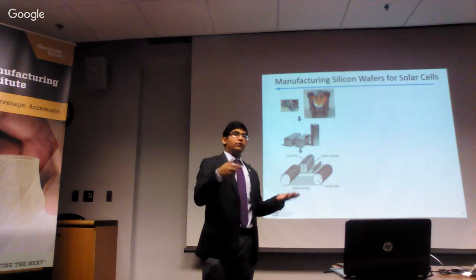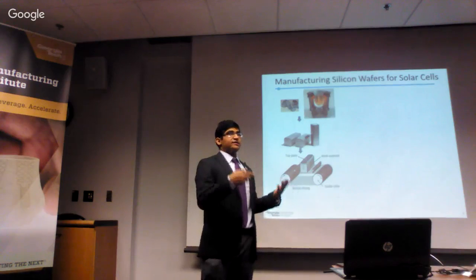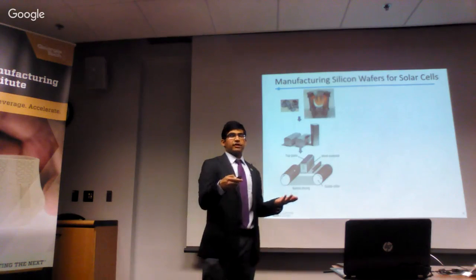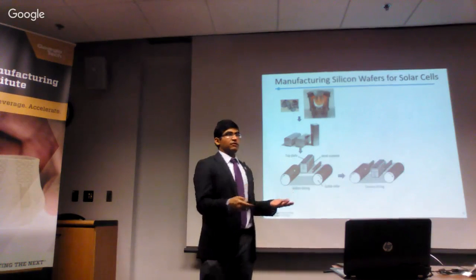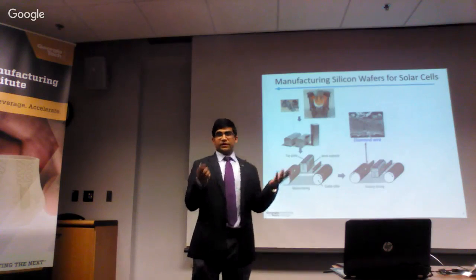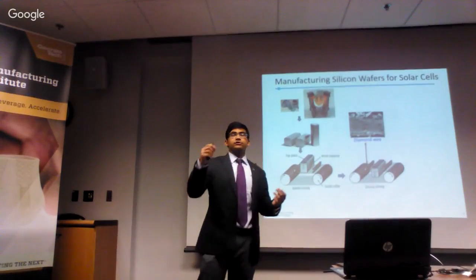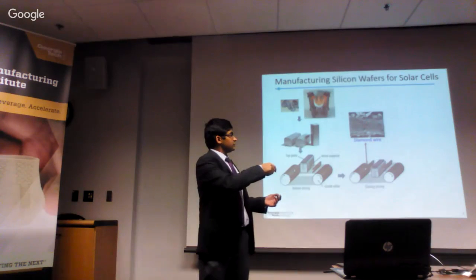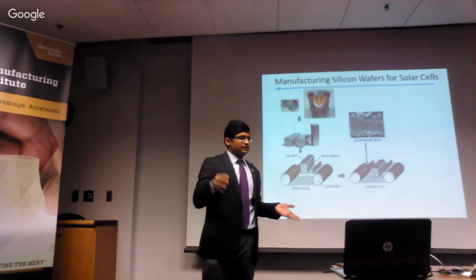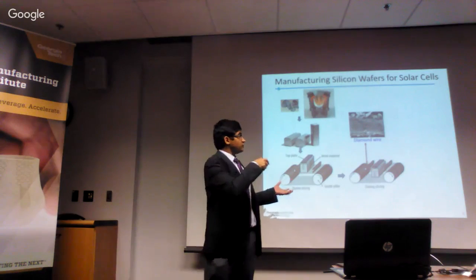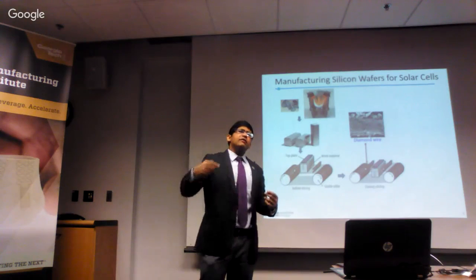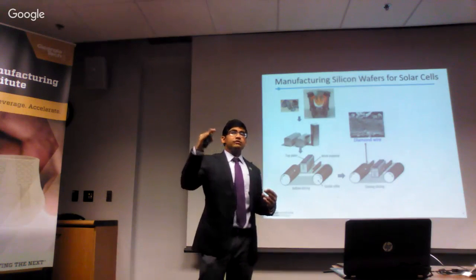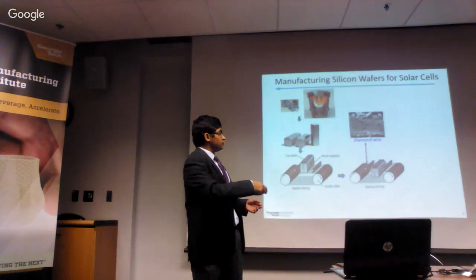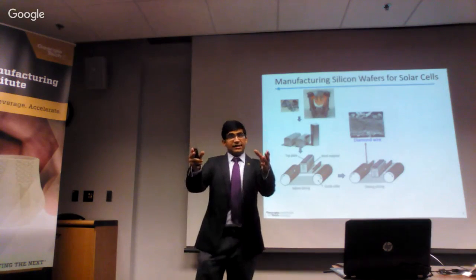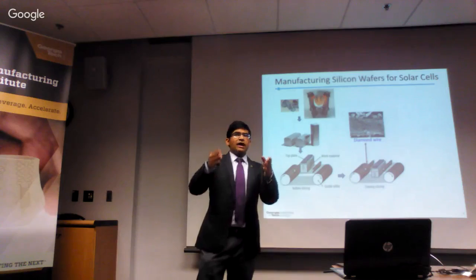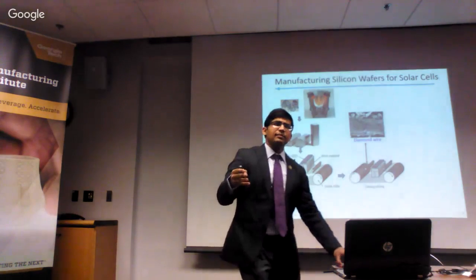Now, both this mono and multicrystalline silicon are then sliced by an abrasive wire sawing process, which consists of tiny diamond abrasives attached to the steel wire using nickel coating. As you see here, these are 10 to 20 micron size abrasives attached to the steel wire. The wire is running at a very high speed, 10 to 15 meters per second on these two rollers, whereas the silicon ingot is going down at a very slow speed, less than a millimeter per minute.